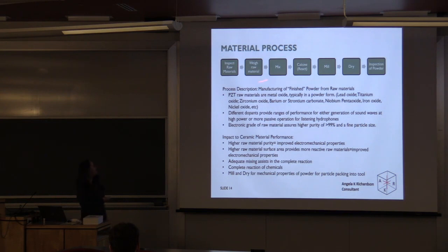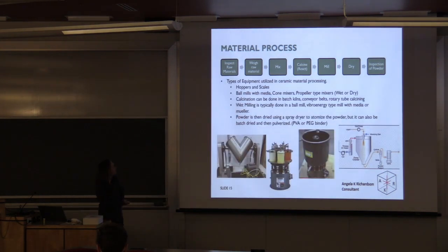Okay. The next, after you've inspected those raw materials, you're going to weigh them, mix them, react them, calcination once again, and then mill them down to a fine particle size. I'll go to the next slide. And then dry the powder and inspect it. What I have shown here at the bottom is some of the industrial equipment that you might utilize. A V-cone blender here for mixing of the raw materials, vibra-energy mills here, which can be used either for mixing or for the milling process to reduce the particle size, and then drying.